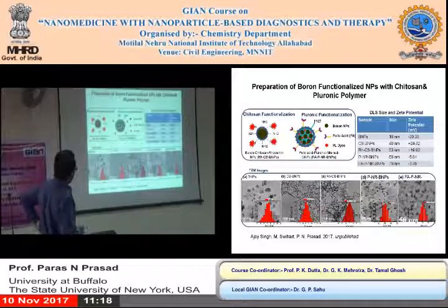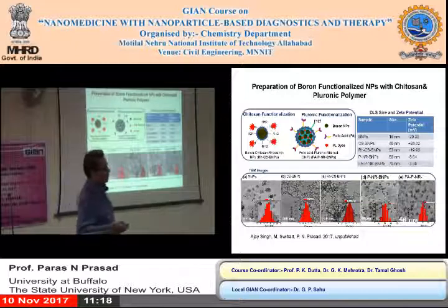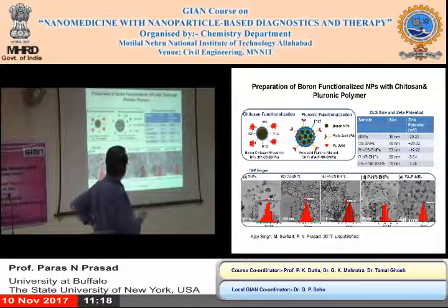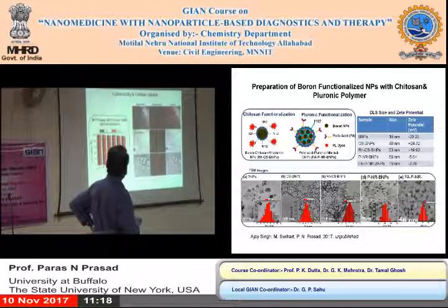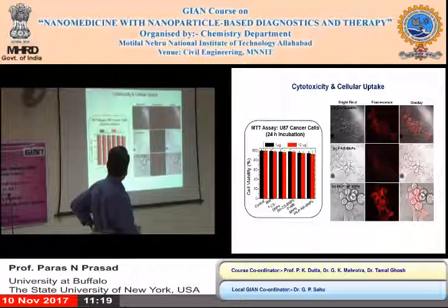We have done a lot of characterization. Their sizes range from 18 nanometer to 70 nanometer, so we can select which size could be most effective for generating alpha particles. We have done toxicity studies, and they show that the particles are fairly non-toxic. Cell viability is very good.